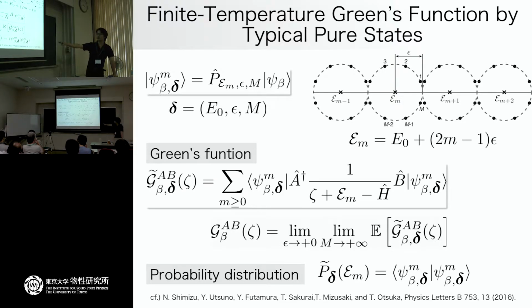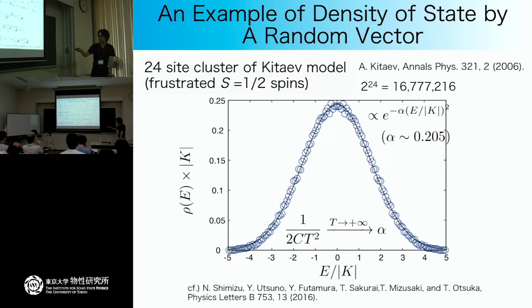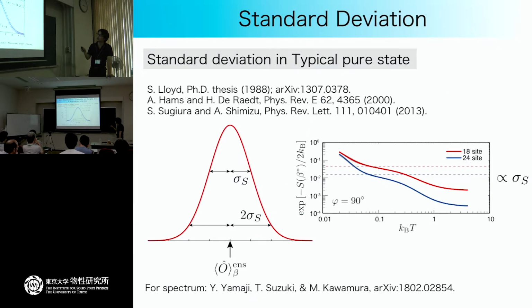This kind of probability distribution is also used in nuclear physics by these authors, including Professor Sakurai, who developed the Sakurai-Sugiura method. And this is a typical example of the density of states. Here I applied the method to the 24-site cluster of the Kitaev model and obtained the histogram of the density of states. The horizontal axis is the energy, and the vertical axis is a histogram of how many states appear in some small discretized energy range. This looks more or less like a Gaussian distribution. And actually, this width is related to the high temperature limit of the heat capacity.